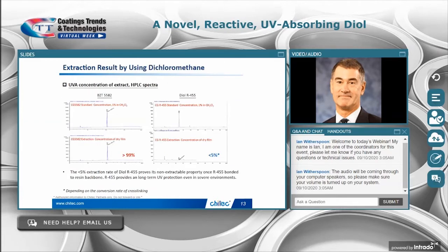Okay, now here are the results of the extraction experiments. We did quantitative analysis by HPLC, and you can see we got almost quantitative extraction. 99% of the benzotriazole 5582 was removed with a methylene chloride extraction of the cured film. And for the diol R455, it was very difficult to detect. Less than 5% was extracted. So our theory really works. We are tying down our benzotriazole into the film, and it does not migrate.